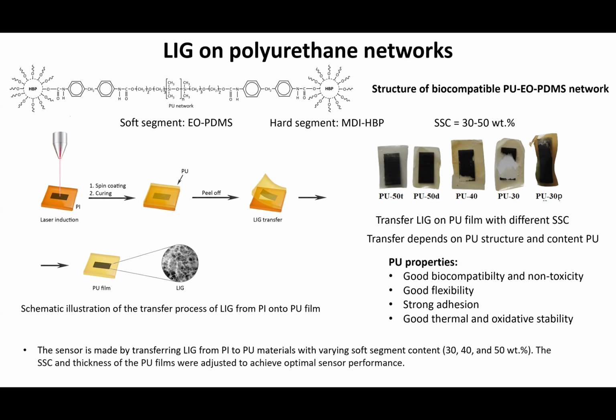Polyurethane is an amazing class of polymers. It has good biocompatibility. It's very non-toxic. It's highly flexible, stretchable. And what we found is that the adhesion of graphene to this is very strong. Once you transfer it, it will not budge. You can try to scratch it off, but it's very difficult.